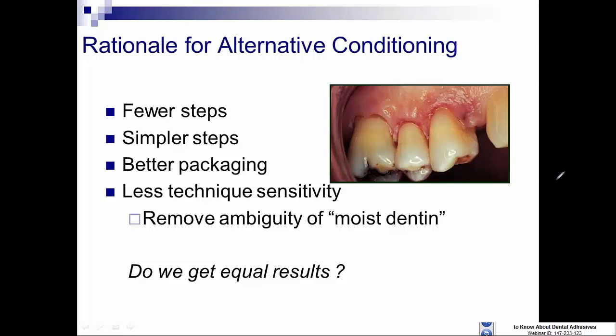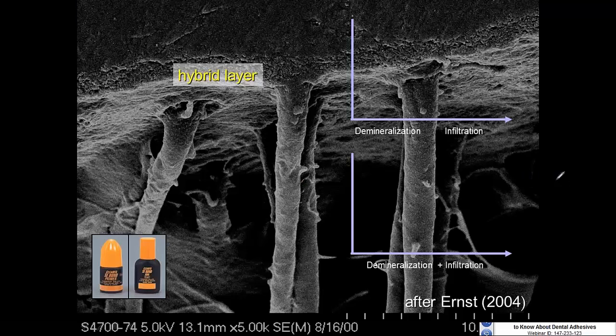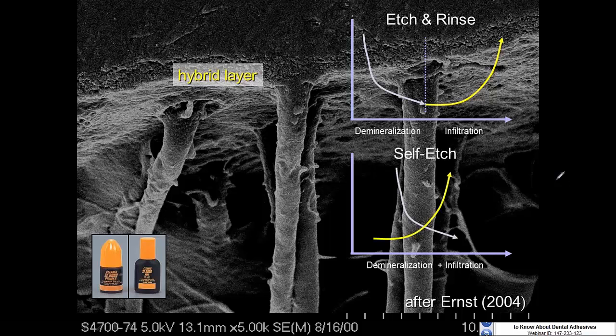Now, what we're talking about with a system like SE Bond or Prompt L-POP or more recent systems like Xeno 4 is with an etch and rinse system, we demineralize, stop, and we resin infiltrate. With the self-etching systems, these are done simultaneously, which means the collagen is never exposed, so it can never collapse. So the demineralization and penetration occur at the same time.